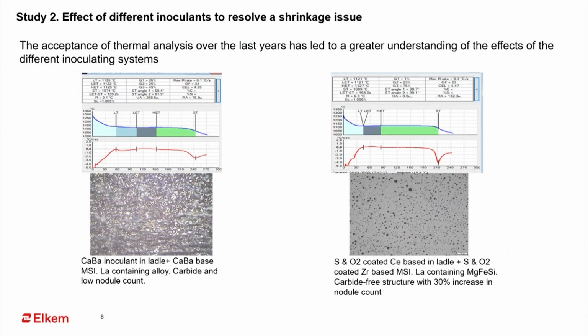nodule count and nodularity. So you can see on this left side, that picture is with carbide, and that melt was produced with calcium barium inoculant, but the magnesium in both cases is the same, lanthanum, only the inoculant was different. On the right side, it is cerium containing and zircon containing inoculant, two-stage inoculant. Both inoculants are coated in sulfur or oxygen. So you can see this drastic change, that I have marked in this green portion, that G3. When your nodule count and nodularity improve, definitely in thermal analysis you will get the highest G3. So always target how we can improve the G3 factor.